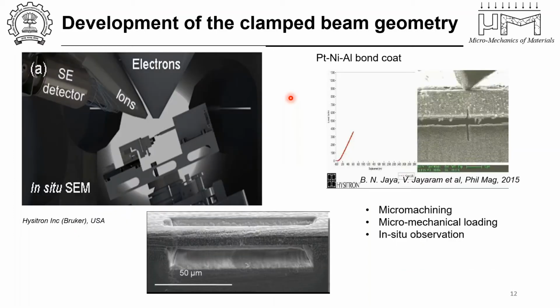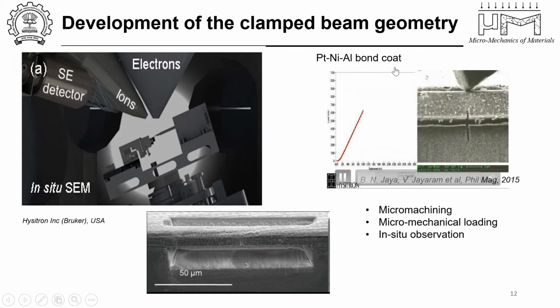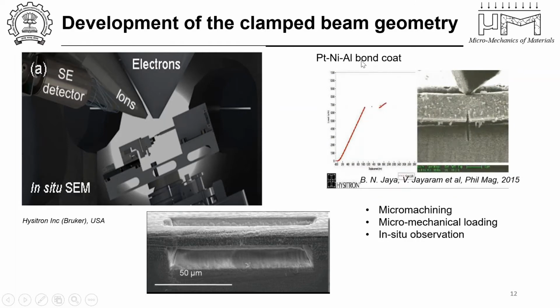So we went ahead and tested a particular sample. In the present days, we have various facilities for micromachining, like focused ion beam machining. We have facilities to micromechanically load them using a nanoindenter, and you can watch it in situ using an electron microscope. So that was what was done here. If you look at the video of this particular clamp beam, which is being loaded now, you can watch what happens as the crack tends to grow. This is a brittle intermetallic material, platinum nickel aluminide. But you see that the crack grows progressively for some time, and then it actually stabilizes, and the material is able to take higher and higher loads.